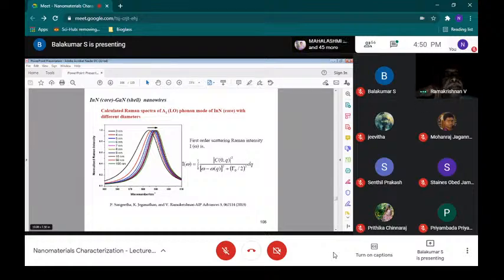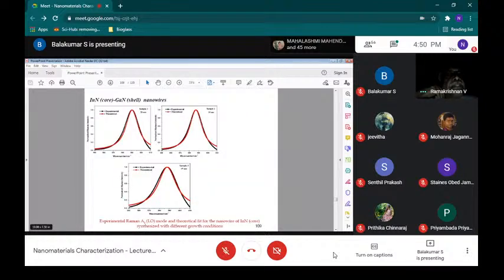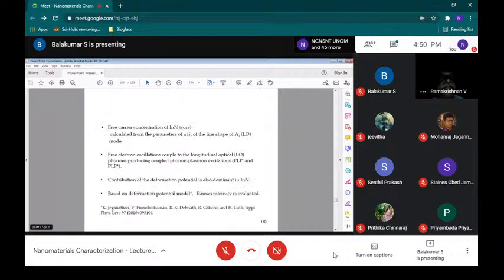Next slide. So it comes to 20 nanometers, 15 nanometers, 15 nanometers. So for 3 different materials, in 3 different cases, we try to superimpose the best fit. What is the best fit we can have for the data? So in one case, it tells the column size: it's 20 nanometers, 15 nanometers, 15. Next slide. So you can tell the free carrier concentration. Next slide.